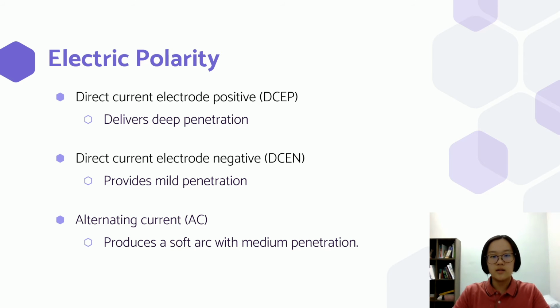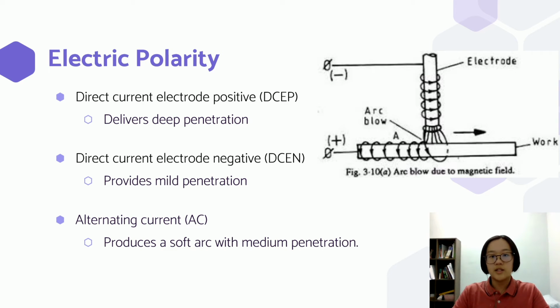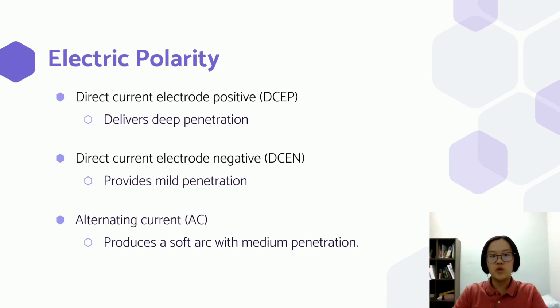When using the direct current, the welding arc can be affected by the arc blow, which is a deflection of the arc from its normal path due to magnetic force. For this reason, some people would choose alternating current to avoid arc blow. Alternating current will produce a soft arc with medium penetration.